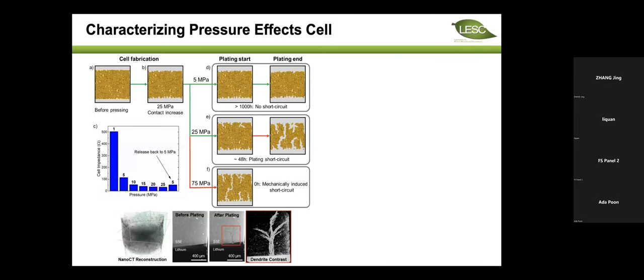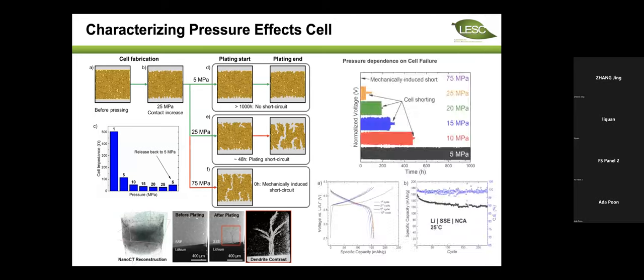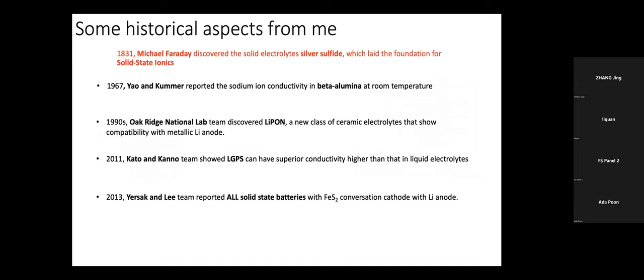The lithium metal continued to be a problem for solid state batteries. In all our cells, at a very low critical current density, something around 0.3 milliamp per centimeter square, lithium metal can cycle if you lower the stack pressure below 5 megapascal. When we do the synthesis, we go to very high pressure to establish the contact, because if you don't have a good contact, you have a lot of void and a very high impedance. So the impedance needs to come down and then go to low pressure. But honestly, these kind of cells are not practical because the critical current density is so low. So up to today, I have not solved the lithium metal challenge.